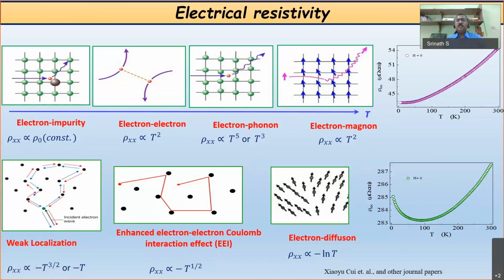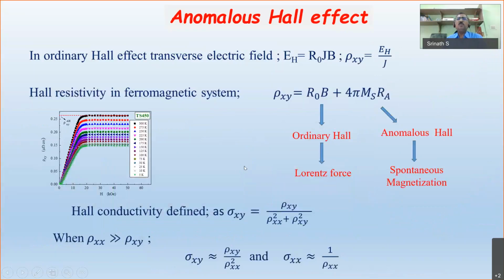So what we did is we did very detailed transport measurements, and then tried to find out what are all the responsible mechanisms and what is the temperature range, so that we can understand these things. And we also did another important aspect called Hall effect, anomalous Hall effect. So in the ferromagnetic materials, apart from the usual Hall effect which we see in semiconductor pictures, materials will have an additional contribution to the resistivity or Hall effect because of the spontaneous magnetization. So we have seen that, and then we tried to understand and estimate what is the contribution of that.